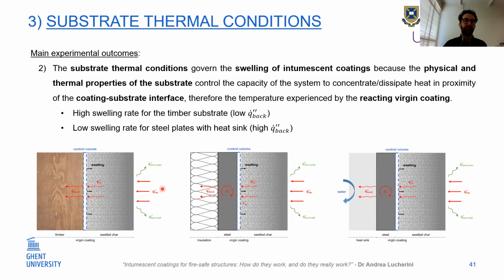On the other hand, I have a coating that is exposed to heat and applied on a timber substrate. You can imagine that timber has different thermal properties than steel plate. In particular, the thermal conductivity of timber is much lower than steel. So timber concentrates heat much faster at its surface, so the temperature of the swelling coating rises faster. As a consequence, I achieve the highest swelling rates for timber substrate, so low losses at the back. And I achieve low swelling rate for steel plates with heat sink, so with high losses at the back.